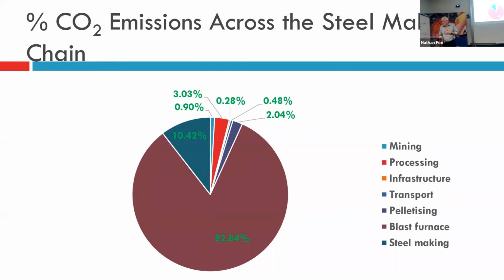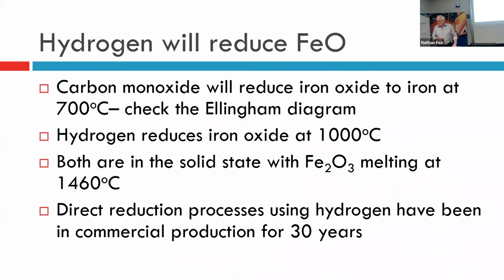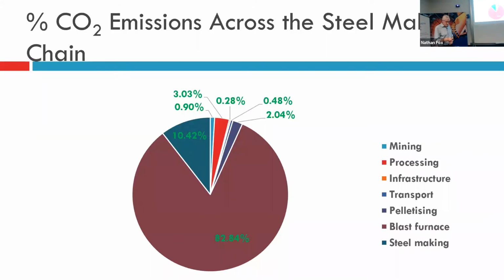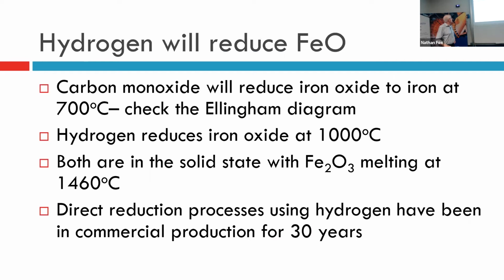Hydrogen will reduce iron oxide. We don't have to use coal and carbon to produce iron. Carbon monoxide will reduce iron oxide to iron at about 700 degrees Celsius, and that's when the iron oxide is still in the solid state. So that's how reductions are happening in the blast furnace. Hydrogen reduces iron oxide at about 1,000 degrees C. It might be a bit less.